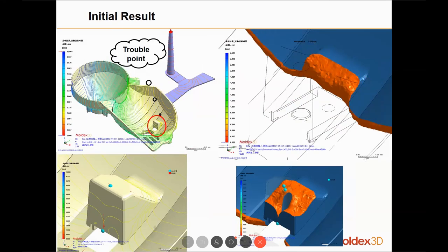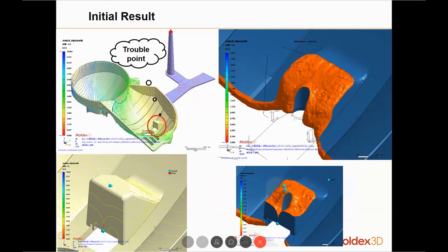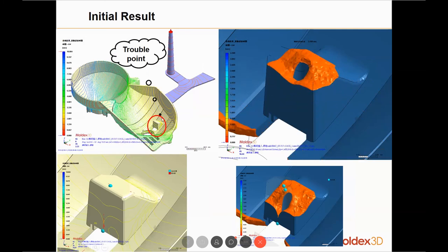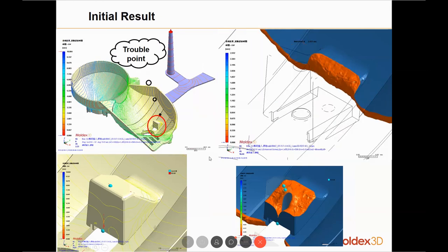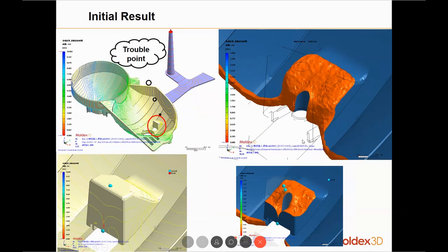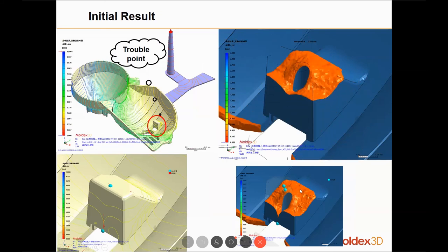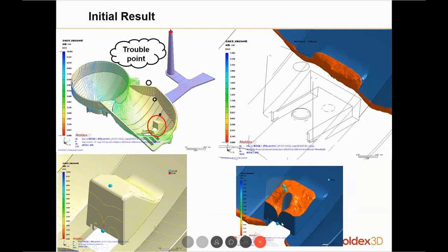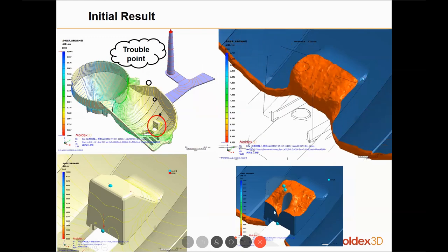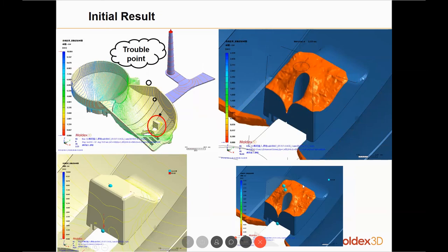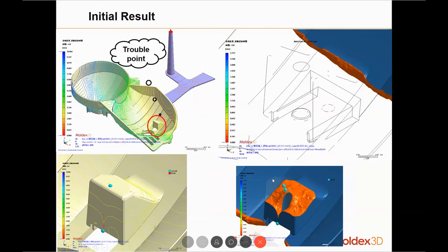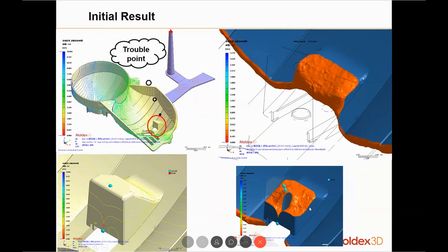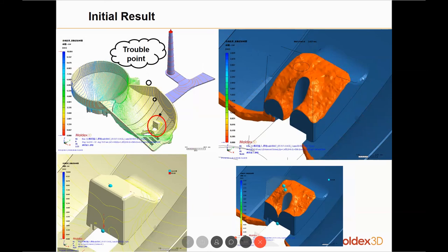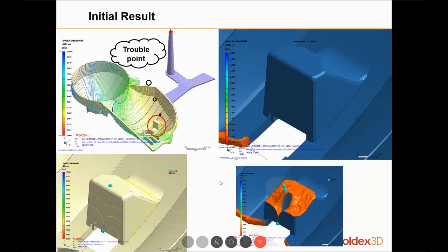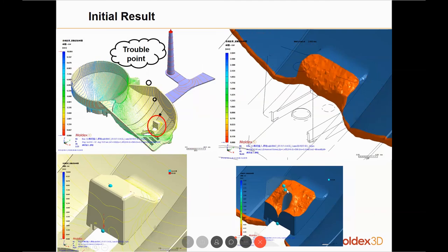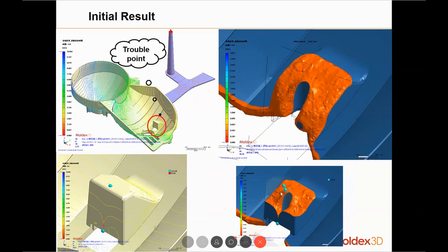Okay, so the initial results with their initial design and process, if we take a closer look at this trouble point, as you can see from the melt front, the melt flows through the whole bottom region first and creates a closed area over here. So we have a completely closed air trap in this region, which makes it almost impossible for air to escape from this region if there is no venting over here, which can be very difficult to design.